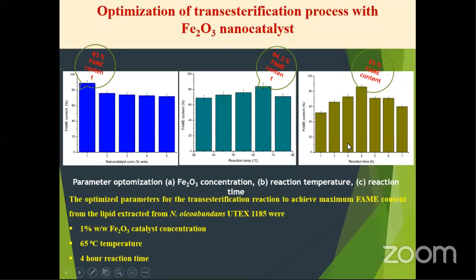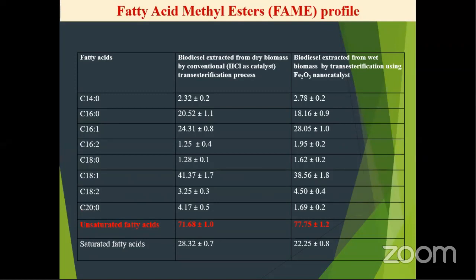biodiesel. And the reaction time is much lower than the conventional process. Usually it is reported that for the production of biodiesel by using HCl and NaOH, it requires 7 to 8 hours. It was already reported. But in this case, we achieved the biodiesel within 4 hours of reaction time with 85% yield. Then after extraction and transesterification process parameter optimization, we have to find out the characteristics of the